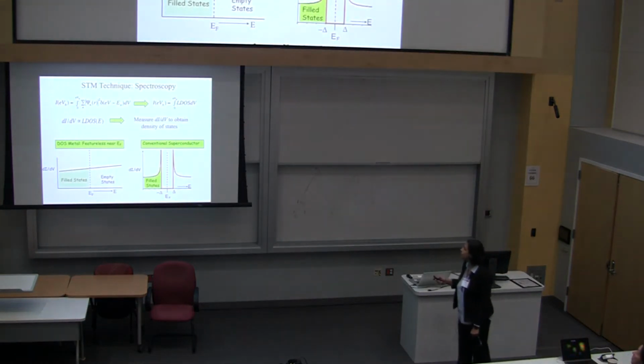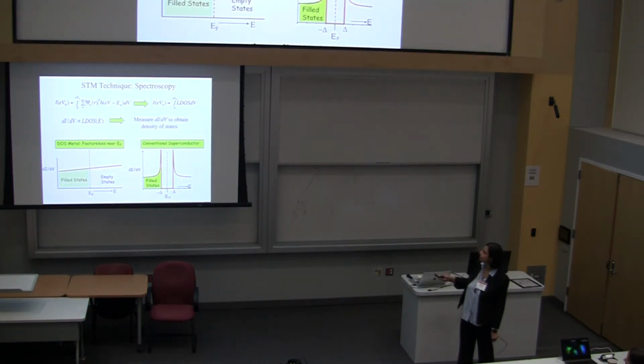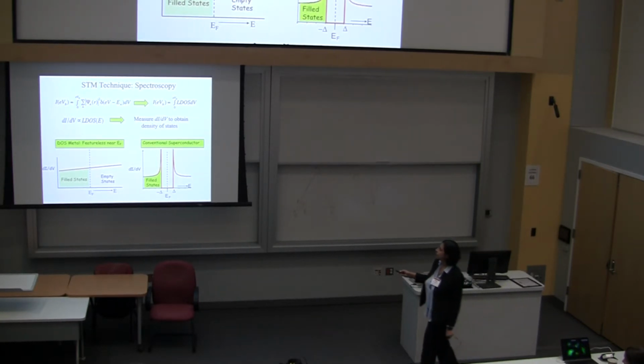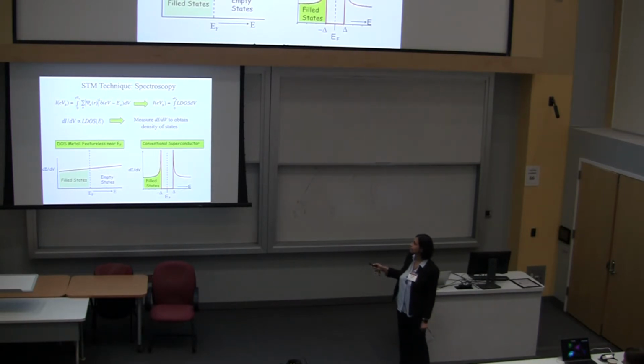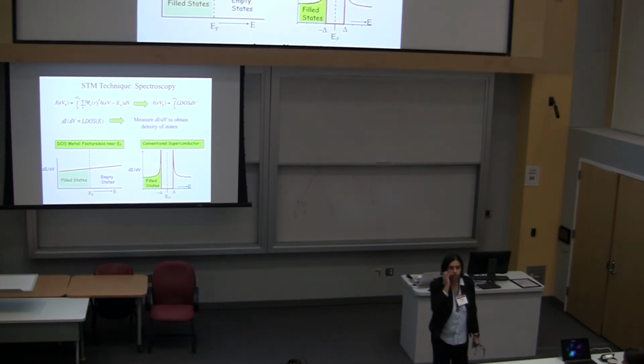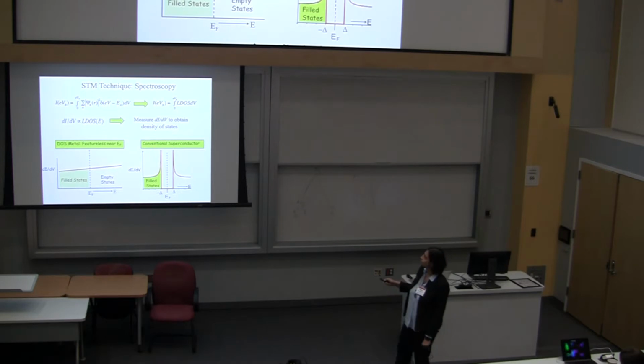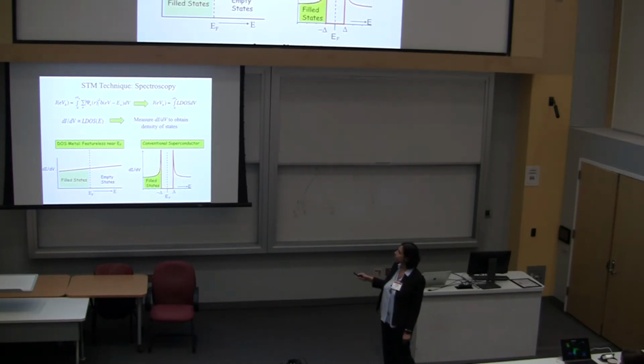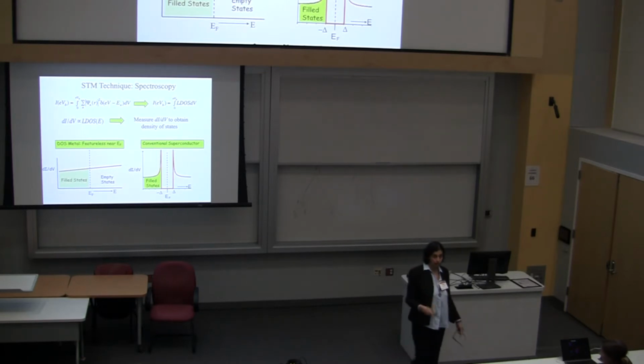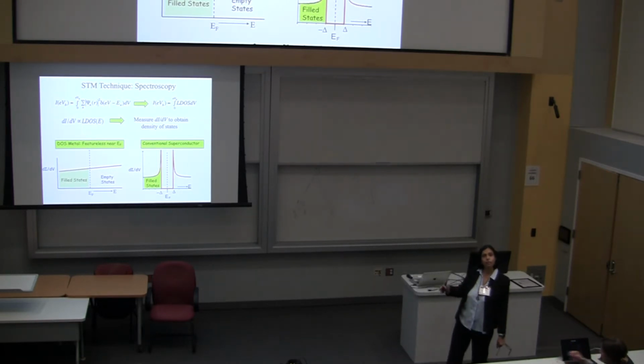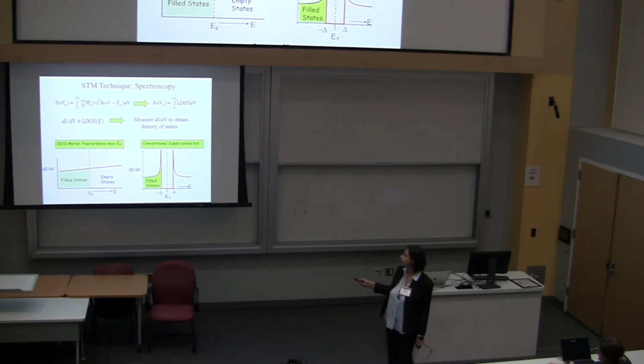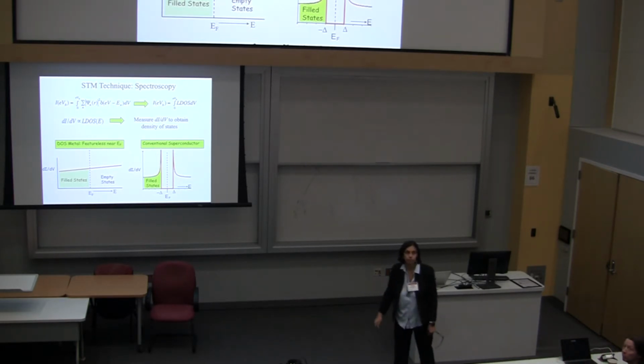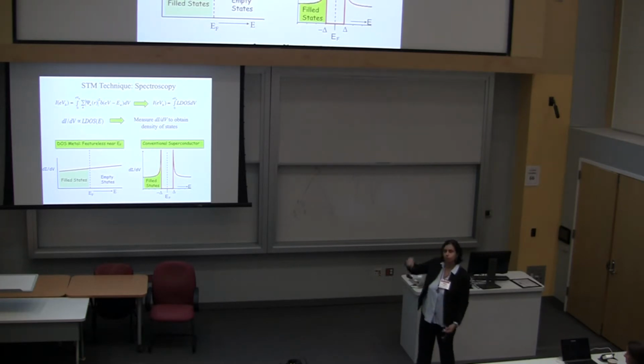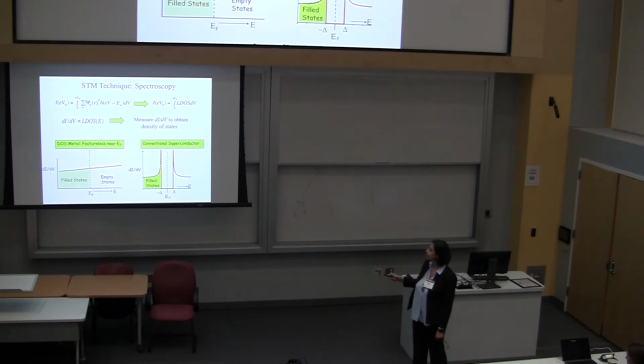But then, because in the STM the current is proportional to the integrated density of states, the differential conductance, dI/dV, is actually proportional to the density of states at any given energy, okay? So what we can do is measure this differential conductance either by measuring I versus V and then differentiating that, or much better, we use a lock-in technique to directly measure dI/dV as a function of the bias voltage.